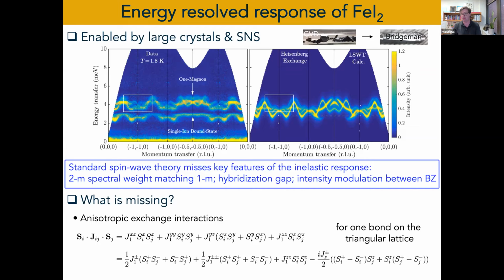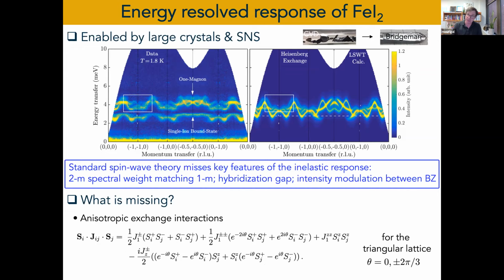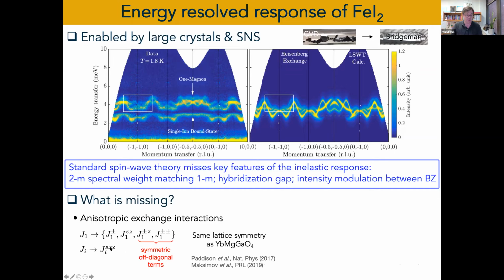So it turns out that this parameterization is easier because when we have several bonds at different angles, we can generalize this Hamiltonian. But so that's some details of the way we parameterize this. The message is just that we let all interactions be spin anisotropic on nearest neighbor interactions, and we let all interactions be of the XXZ type on all other bonds of the system. And when we do so,